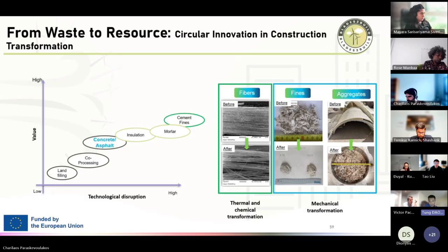So after 3 years of the BLADES2BUILD project, today we can generate different raw materials that are ready to be integrated in different existing products. You can see that we can produce clean recycled fibers by using thermal and chemical transformation. But in other cases as well, we can produce fines and coarse and fine aggregates with the mechanical transformation. And for the concrete application that I mentioned previously, we use the fine and coarse aggregate coming from the mechanical transformation for the upcoming development. So please move to the next slide.